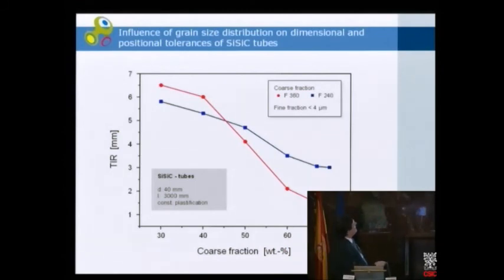There was a parameter called TIR, total indicator reading. This summarizes the bending, the curvature, the ovality by a turning measurement, high precision measurement, tactile measurement on the tube. And the original specification was to achieve 1 millimeter length per 1 meter length of the tube. That's where we started, and even in the early phase there was no competitor. And that's where we ended.